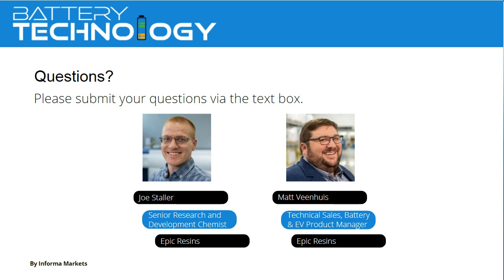Is urethane susceptible to moisture after it's fully cured? Absolutely, yes. As we talked about in that slide, the backbone of the polyurethane does have some portions that can be attacked more by water than epoxy systems. However, depending on how we formulate the cross-link density of the urethane, we can adjust that along with the type of raw materials. There are certain types of raw materials that are more or less hygroscopic when cured. So again, we tailor the backbone of that final thermoset polymer to accomplish the properties you want in your final application. And the urethanes are still formulated to protect the parts of the circuitry, or whatever the application is, against moisture getting to where you don't want it to go.